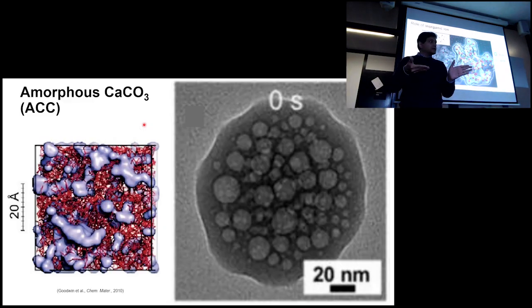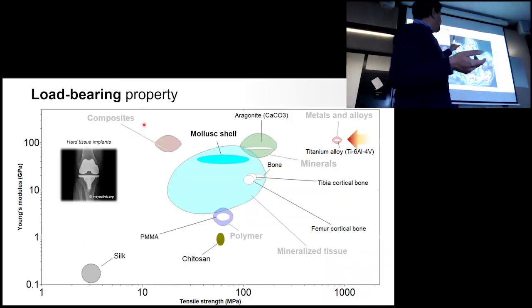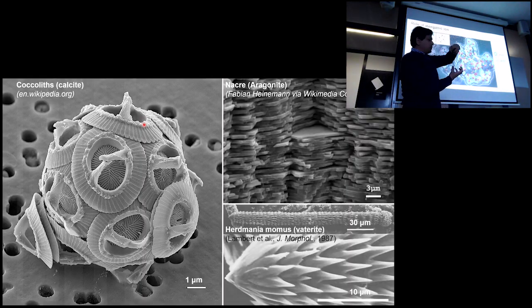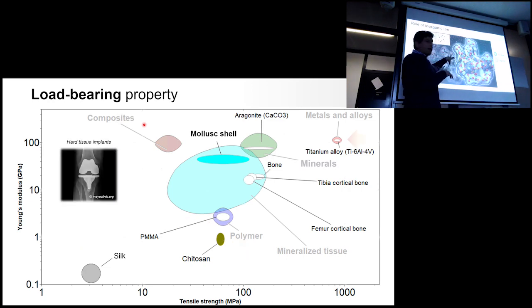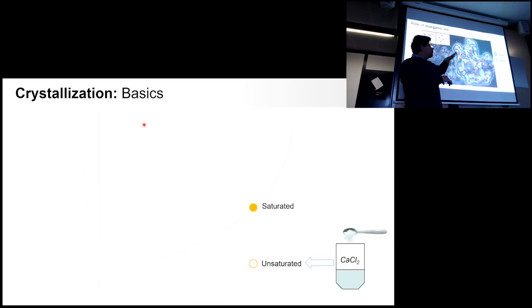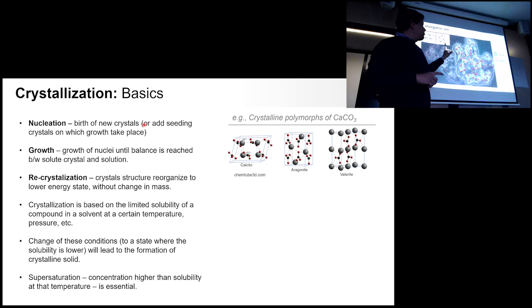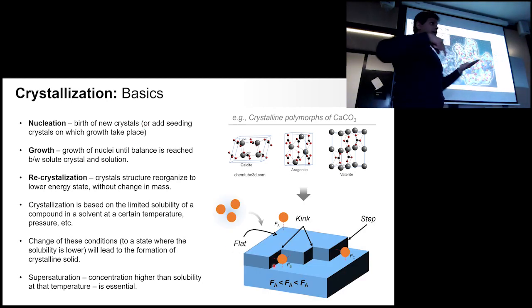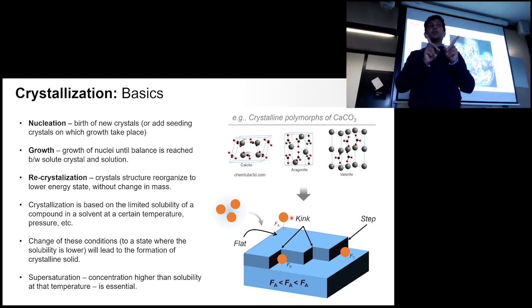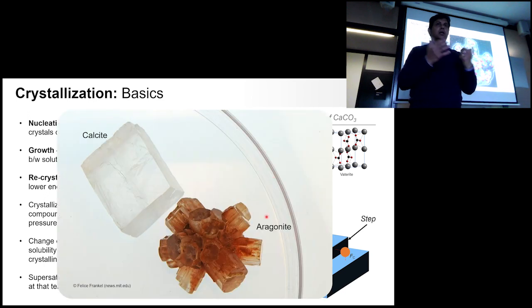These are called kink sites. So magnesium experiences attractive forces in those locations and binds onto those kink sites and blocks them, which is why when you have mineralization of aragonite happening with magnesium, you get structures which are high aspect ratio. You get needles, you get these funny shapes, spicules and such.